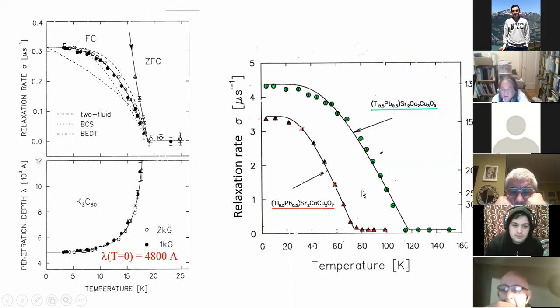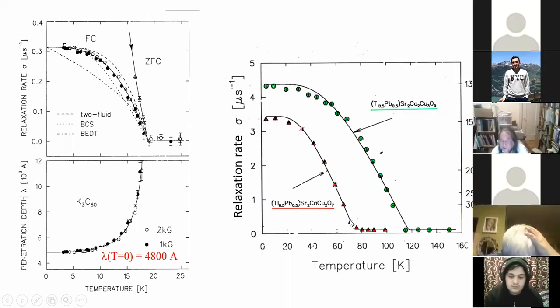And we are seeing that this damping rate changes this way. And so immediately what you can say is that there are more of this superfluid density, this carrier NS over M stuff, which we usually call superfluid density, in the higher TC material than the lower TC material. And you can also determine the penetration depths of each material accordingly.